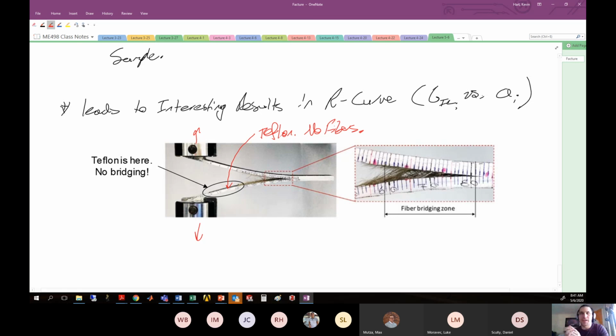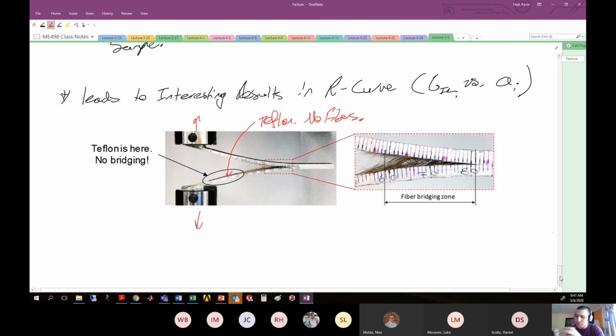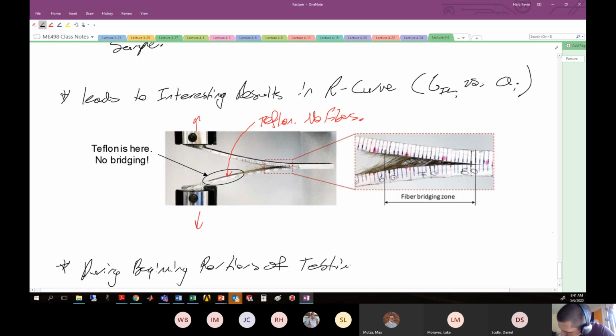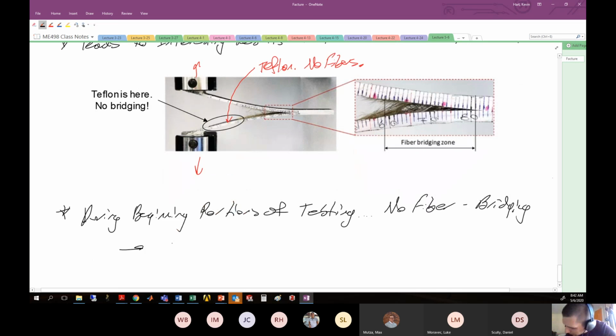So right when you first begin your testing, there is no fiber bridging. And what that results in is lower values of your critical strain energy release rate, because you don't have this Velcro that's holding on and hanging on to sort of cause the sample to stay together. Okay, so during beginning portions of testing, there's no fiber bridging, and therefore G1C is lower.